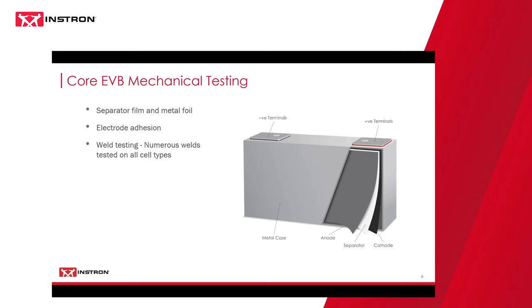For metal foil, this would be like the current collectors, the aluminum and copper foil. We want to make sure it can withstand things like the expansion and contraction during the use of each cell. For instance, different material compounds within the electrode makeup can alter the needs for either higher or maybe lower elongation values or even tensile strength values. So you need to be able to understand those properties of your material.